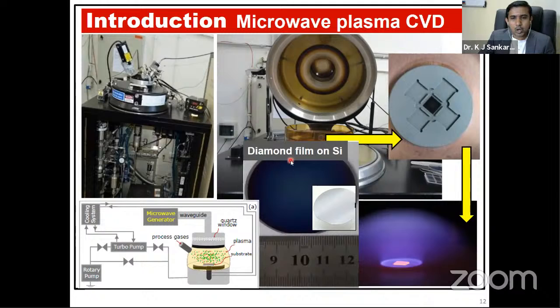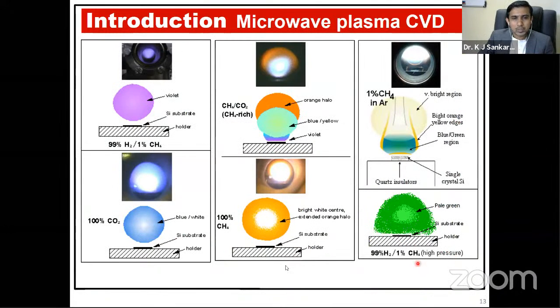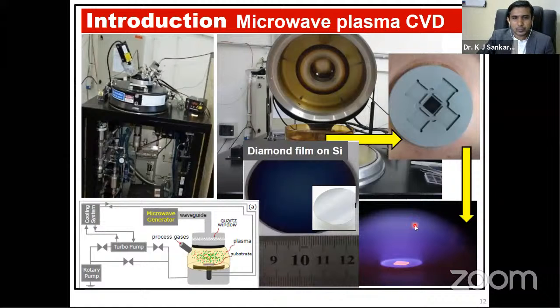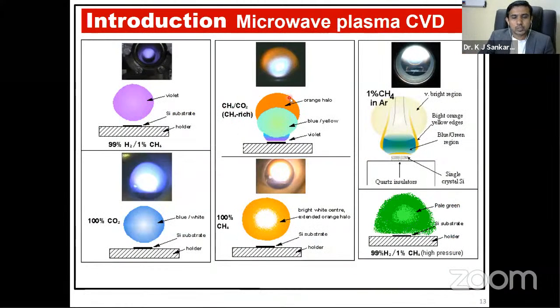This is the diamond film after the growth on the silicon substrate. This is the silicon substrate, which was unseeded, after the growth. You can see a darkish bluish color of diamond films on the silicon substrate. As I mentioned, different colors of plasma result in different morphologies. So what are the different colors of plasma with different process gases? Here I show a very detailed list. When you use hydrogen and methane in a ratio of 99:1, we get a violet colored plasma, which I showed in the earlier slides. And when you use only methane and CO2, the plasma colors vary a lot. In the middle it looks blue and yellow, the bottom looks violet, and the top has an orange halo.